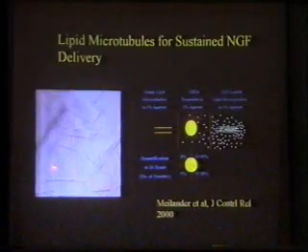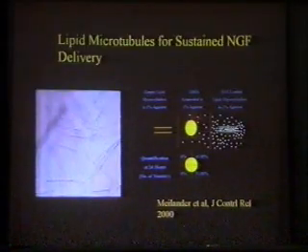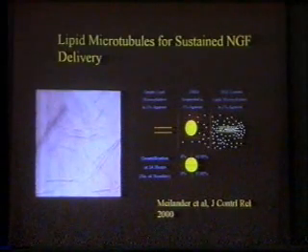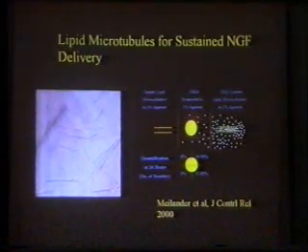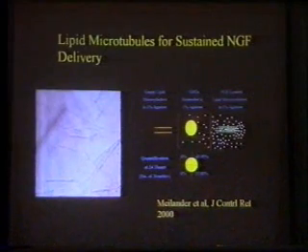These are the dimensions of each of these lines you see here. They're about 40 microns in length and 0.5 microns in the opening. Very high aspect ratio. Think of them as hollow straws that you drink Coke with, except it will take you a long time to drink Coke with these. So they're about 40 microns by 0.5 microns. When you dry these out in the presence of a sugar like trehalose, they're completely dry and empty.